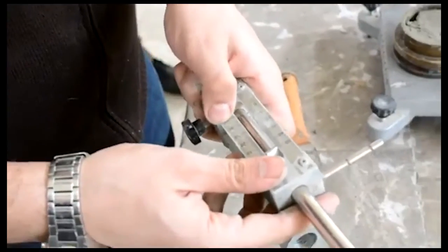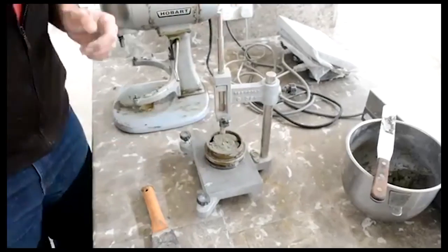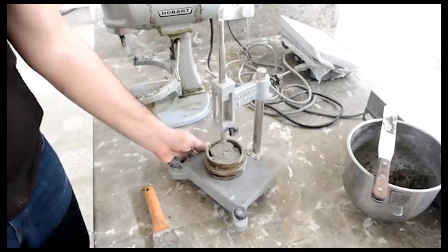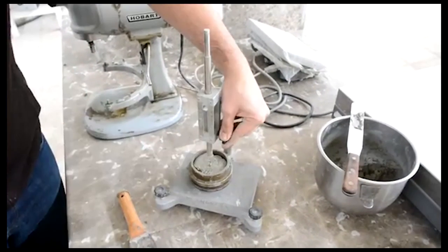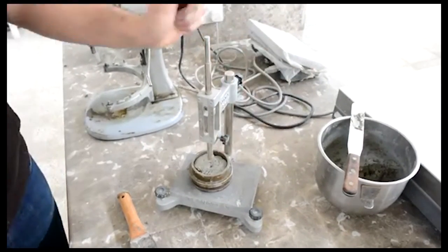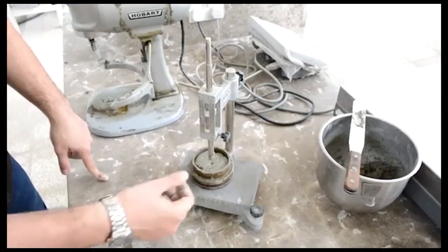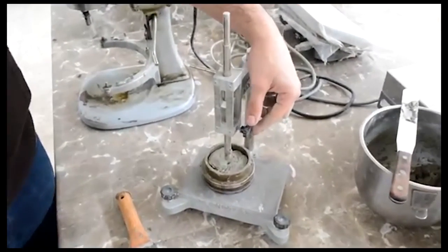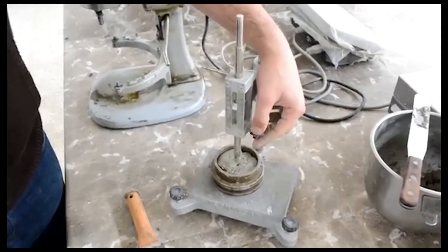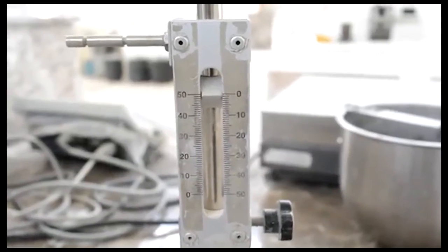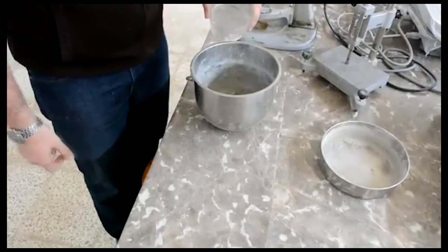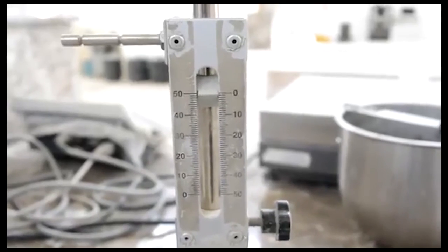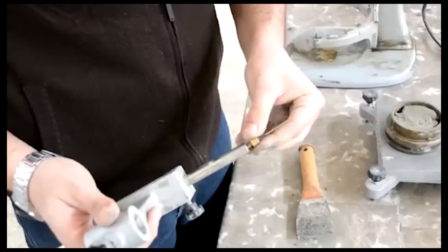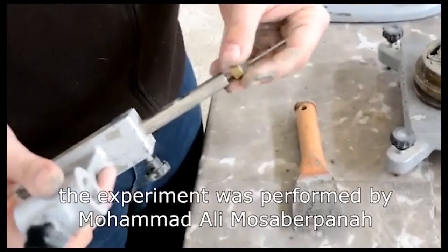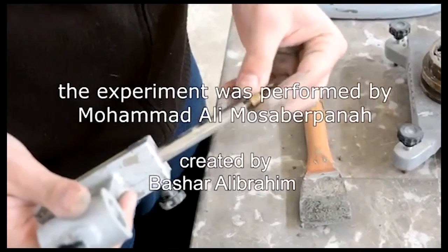Then, place the thick needle on the Vicat apparatus. Set the indicator on 0. Adjust the needle until it comes in contact with the base surface. Release the needle. The needle will penetrate the paste. Repeat this operation every 15 minutes until the needle fails to penetrate the paste. The time between the initial contact of cement and water and the failure of the thick needle to penetrate the paste is the final time of setting. And by that, we were able to determine the setting time of hydraulic cement by Vicat needle.